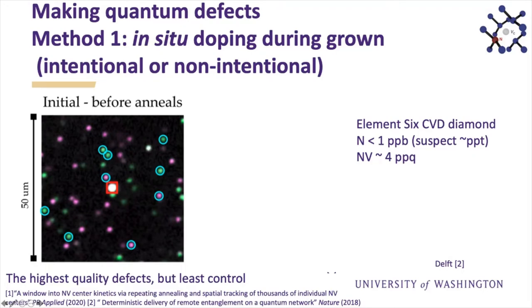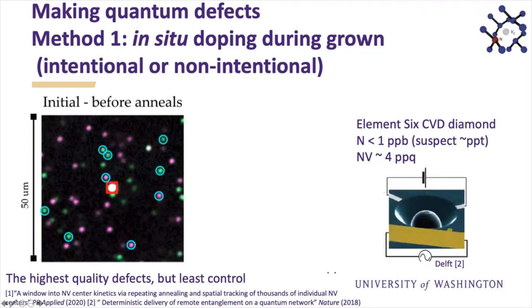We can sit and count these nitrogen vacancies and say actually the number of nitrogen vacancy centers is 4 parts per quadrillion. These defects have the best quantum properties, and they're actually used in quantum protocols, which includes a long distance entanglement between two NV centers, and also a loophole free test of Bell's inequalities, showing the quantum correlation of two of these defects. And they've been used by simply finding an NV center like this that's quite good, and then milling out a lens around it so you can enhance the light collection.